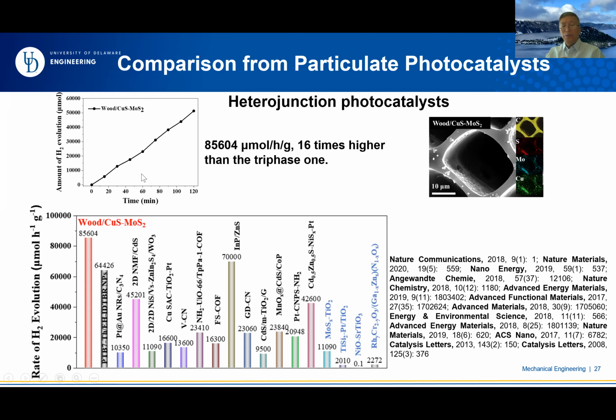We also tried to apply this system to heterojunction photocatalysis. Here we tried a copper sulfide, molybdenum sulfide heterostructure, and we achieved the highest hydrogen production rate. And again, compared to the triphase system, this biphase system increased by 16 times. And also the overall hydrogen production rate is the highest so far in particulate photocatalysis systems.